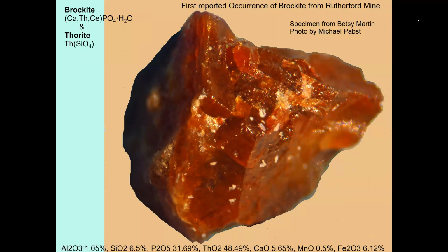This is another small specimen provided to me by Richmond club member Betsy Martin, and it's a mixture of about 90% brockite and 10% thorite. The brockite being a hydrous calcium thorium cerium phosphate, and thorite being thorium silicate. EDS results shown on the bottom. Brockite represents a second species in this presentation not listed in MINDAT, and is the first reported occurrence of the mineral in the pegmatite. Thorite had been first reported by Lumpkin in 1998. Next slide.